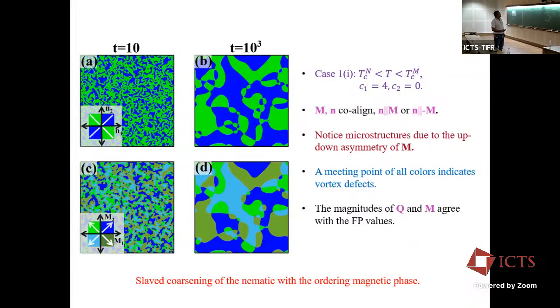What you should do is the following. You start off with a disordered field at t equal to 0. Okay. So that would mean you had an infinite density of blue and green structures. As time goes on, you order into one quadrant or in the other quadrant. Because there's an up-down symmetry, the angle can only be 0 to pi. And as time goes on, the domains become larger and larger. And finally, at the end of the day, at infinity, you've broken symmetry and everything points in one direction. Okay, that's the picture. But sorry, what's your question?